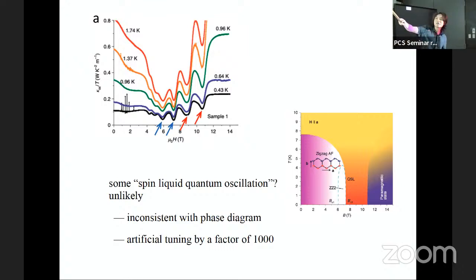But you can see that there are features even before coming into this regime, where there should be nothing weird. Moreover, even if they come up with this spin liquid quantum oscillation to produce this period in the magnetic field, they need to make some very weird claim, like there's some emergent magnetic field that is proportional to the actual magnetic field but a few hundred times larger. Very weird claims. So even if they use quantum spin liquid or whatever, there's no good explanation.